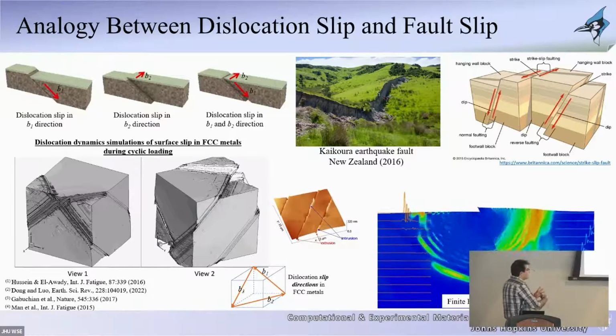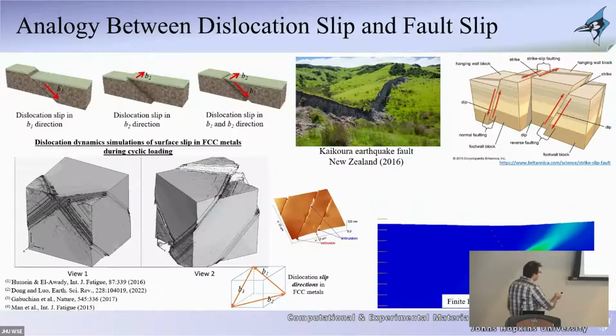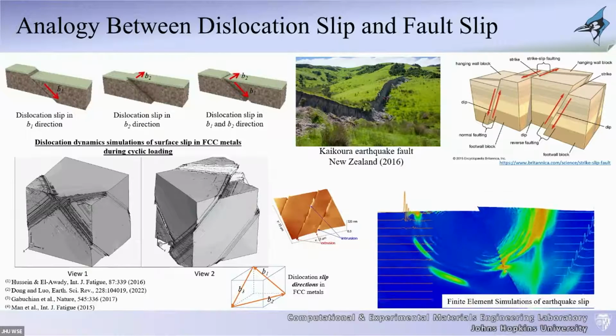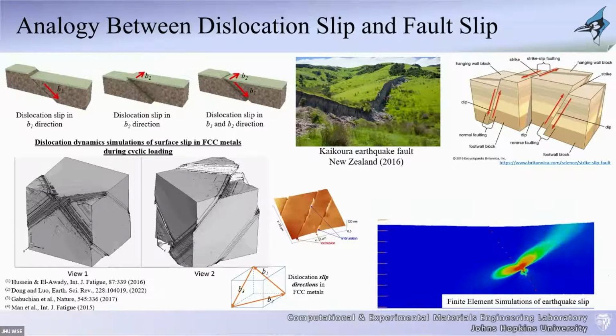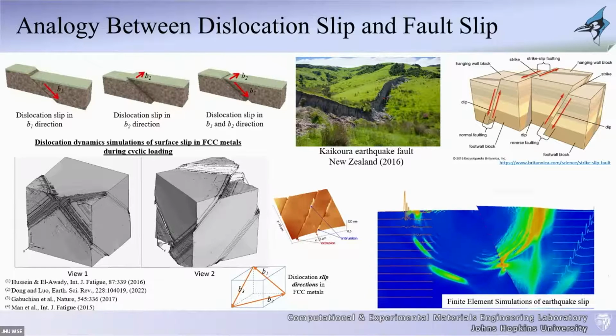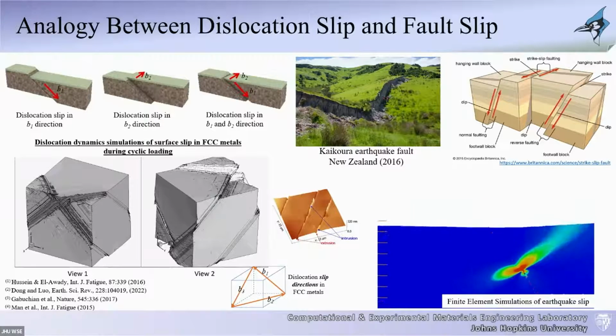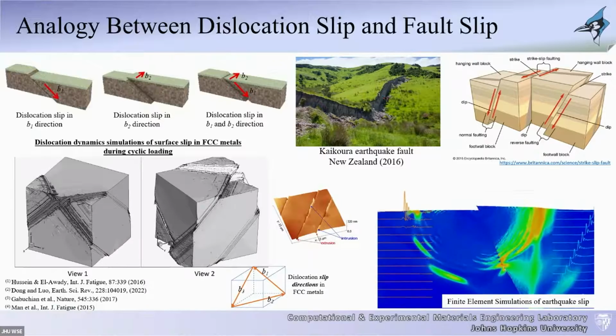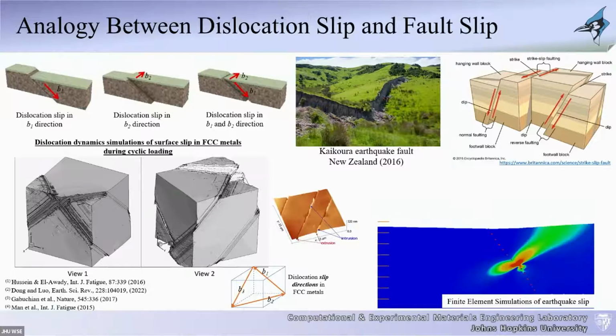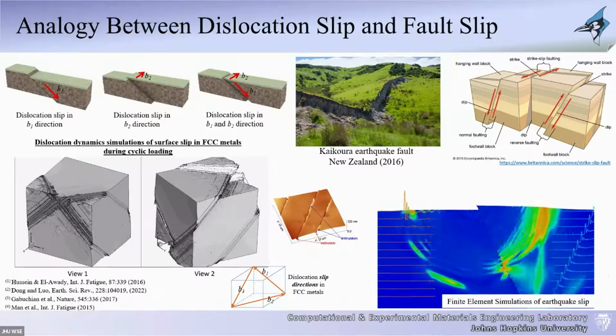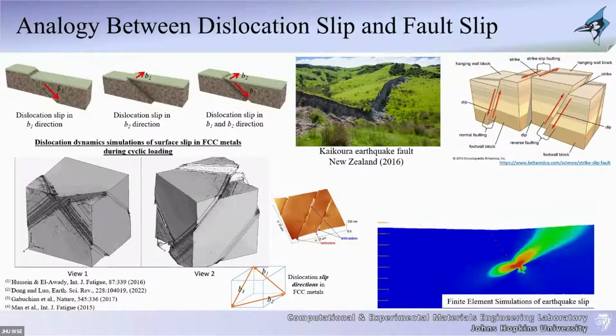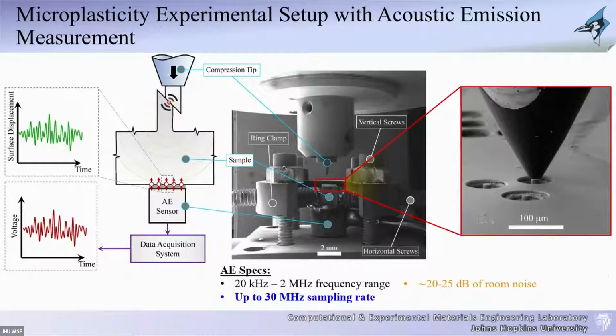In the world of dislocations, it's very similar. The motion of these dislocations as they move, that slipping that happens in the material, induces an acoustic wave in the material. And that acoustic wave you can actually measure the same way that they do in earthquakes. They put sensors all over the place, they measure the displacements. That's exactly what you can measure with dislocation plasticity. So this is where the acoustics came into play.